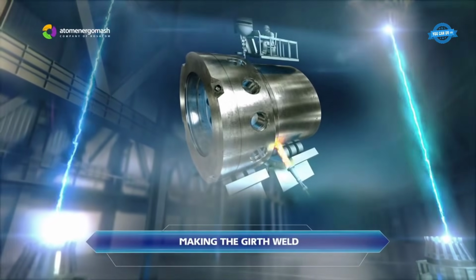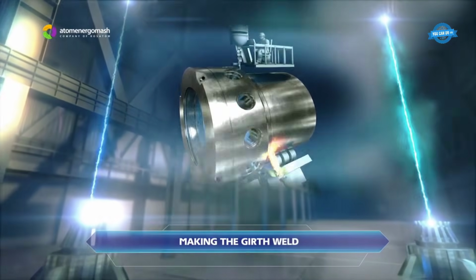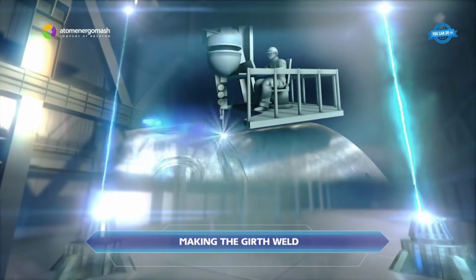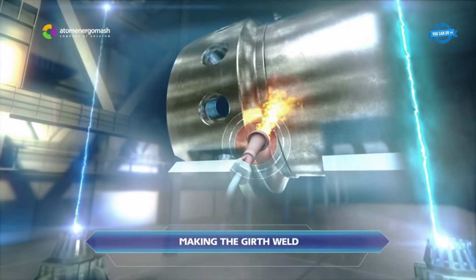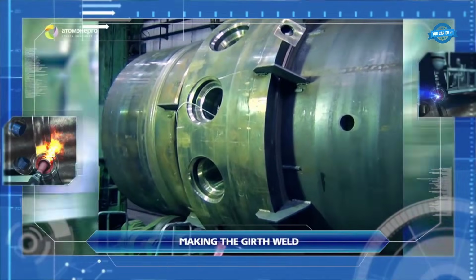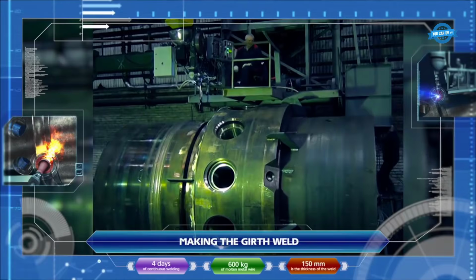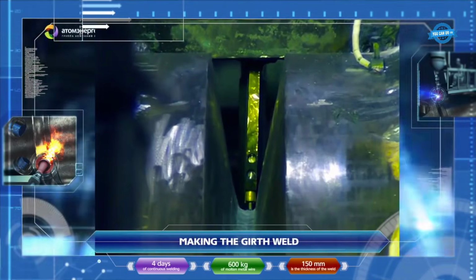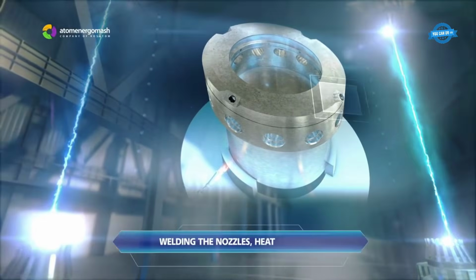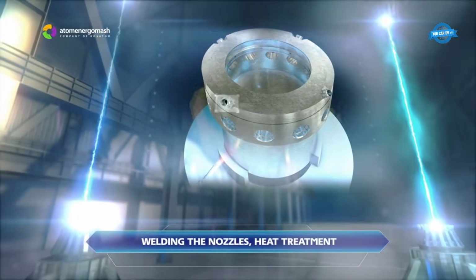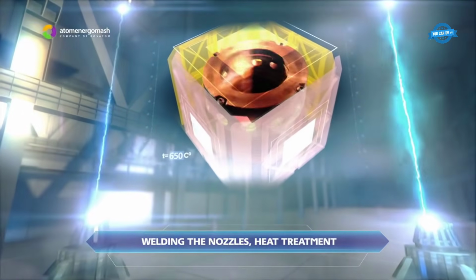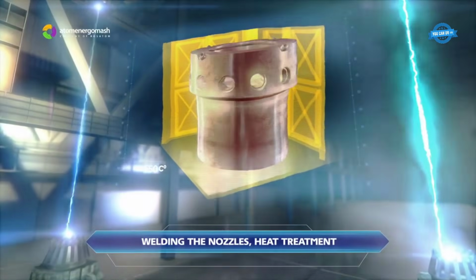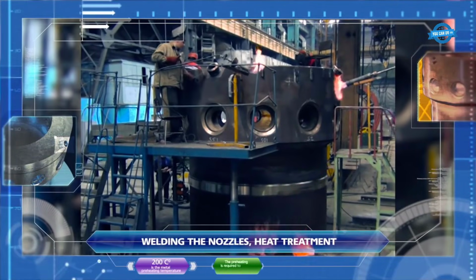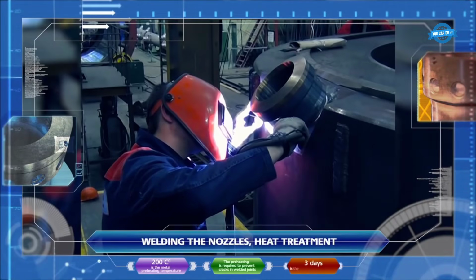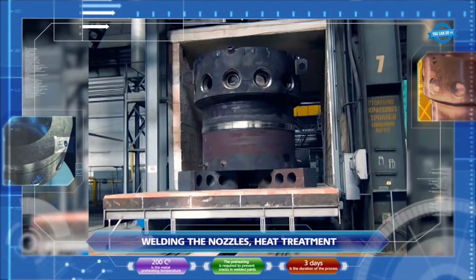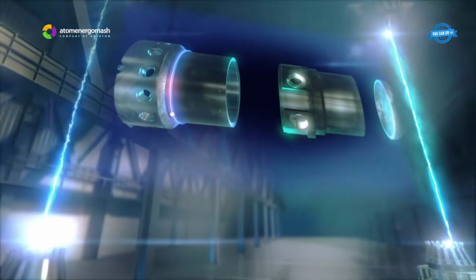Making the girth weld. The girth weld is a critical component that holds the reactor vessel together. It requires 4 days of continuous welding, using an impressive 600 kilograms of molten metal wire. The thickness of the weld measures 150 millimeters. Welding the nozzles and heat treatment. To ensure their durability and integrity, they undergo a meticulous welding process. The metal is preheated to 200 degrees Celsius before welding to prevent cracks in the welded joints. This process takes 3 days to complete.